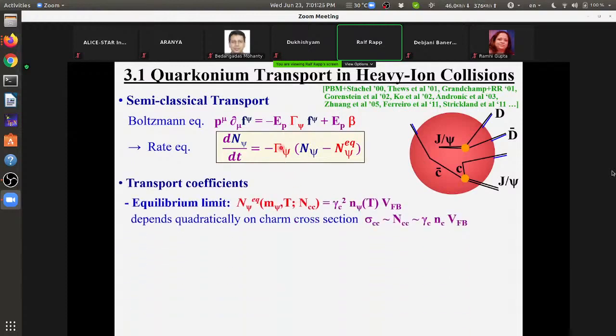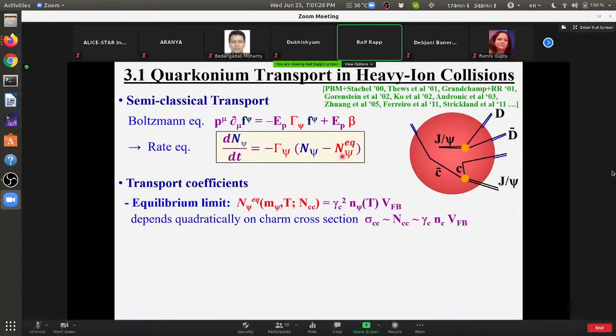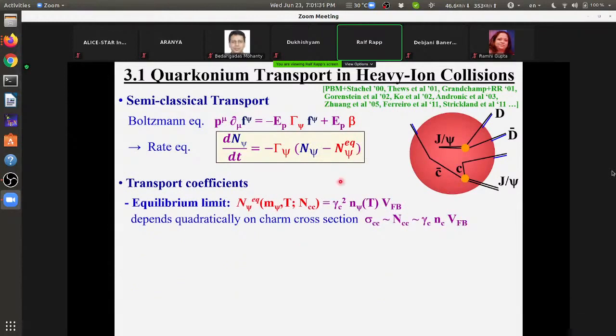A couple of comments on these key transport parameters. One being the equilibrium limit. That is what you should approach to. Every interacting theory should have, in principle, a well-defined equilibrium limit, and that controls the gain term. And that equilibrium limit, let me just say, it depends. The bottom line is that equilibrium limit for charmonia depends quadratically on your input charm cross section, because charm is produced in the early phases, and then you need a fugacity to keep the charm number constant in the subsequent evolution. That's where this, if you wish, chemical potential or fugacity comes from, and the J/psi prime, and so on. Equilibrium abundances depend quadratically on it.